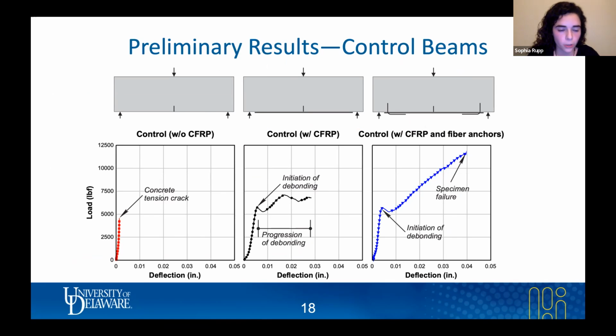I had the chance to work with an undergrad student, Nico Zawadny, and run some preliminary tests on a few RC beams. The RC beams consisted of an unstrengthened group, a strengthened group with no anchors, and a strengthened group with anchors, varying those anchor diameters that I mentioned earlier, as well as an unbonded beam with 1/2-inch anchors. As you could imagine, from 3-point bending of the unstrengthened beam, we saw a relatively low load capacity. The tensile cracks started to form pretty early on, and then the beam failed. However, for the strengthened beam that had no anchors, we saw a slight increase in load capacity.